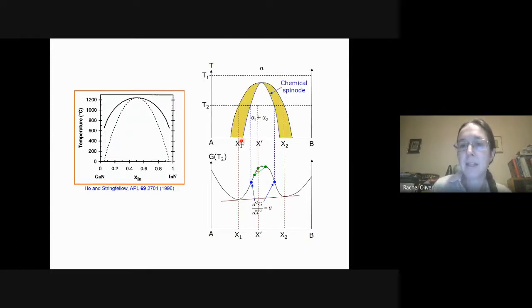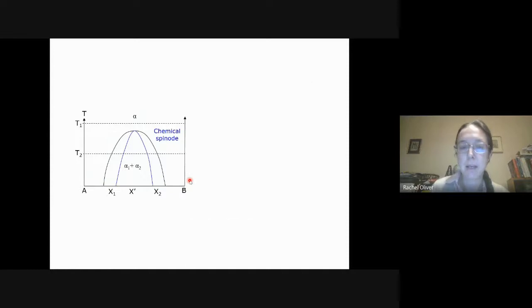Now, what we've calculated there is what I would call a chemical spinode, and that's what Ho and Stringfellow calculated in their paper. But if we introduce the concept of strain in our material and say that A and B have different lattice parameters, and therefore materials of different composition will be strained relative to one another, then that tends to suppress the spinode because of the formation of strain energy or equally of disordered interfaces on decomposition. We call that the coherent spinode.